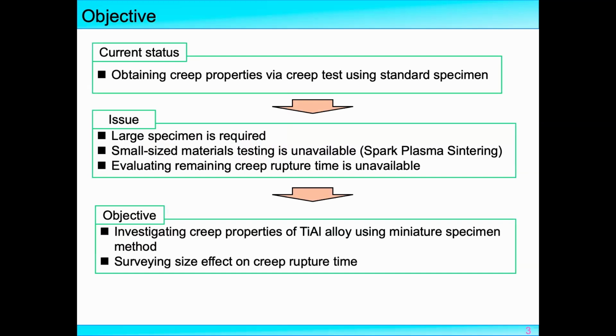Usually, we obtain a new material's creep properties by using the creep testing and using the standard specimen. However, there are some issues in this method. For example, a large specimen or large size material is required for standard creep test. So if we have a new material made by SPS method, as I know the maximum size for material made by SPS method is less than 20 millimeter. So if we want to know the creep properties of this material, testing using the standard specimen method is unavailable. And another problem is that evaluating remaining creep rupture time is also unavailable using the standard specimen method.